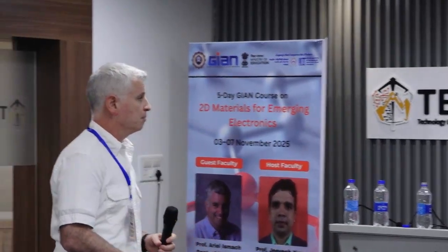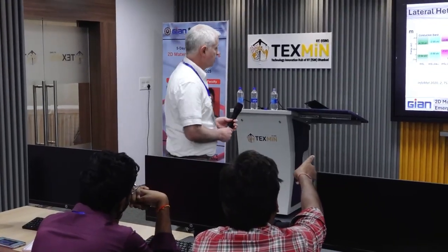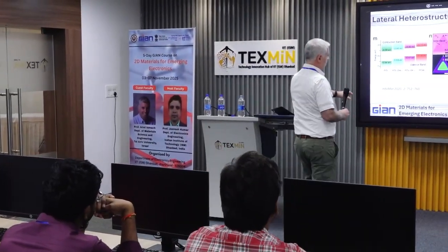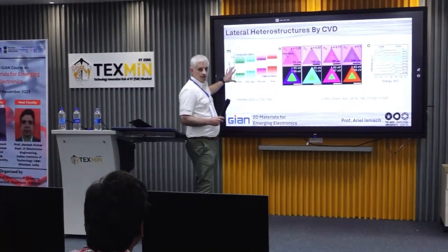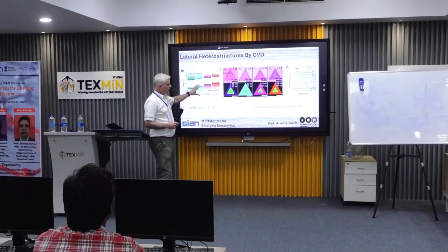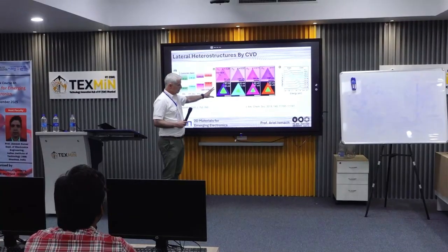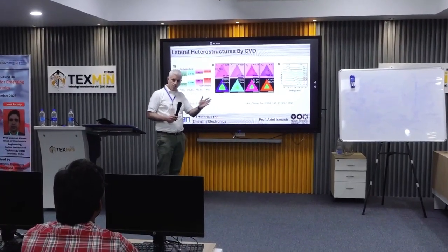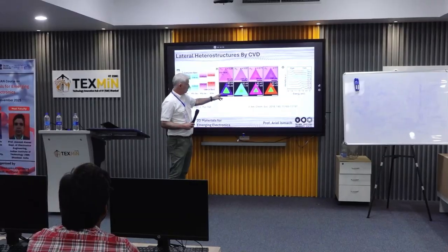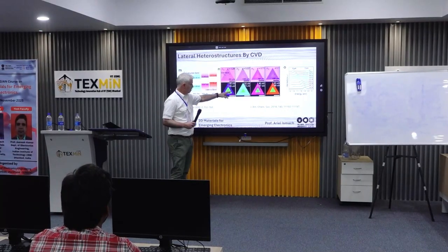So this is possible. This was done by the metal-organic type of CVD (MOCVD), not by the normal CVD. Another one: tungsten sulfur selenide has been synthesized in this state. So this is a theoretical work showing the bands, and this is an experimental work in which they switch the composition during the growth. So therefore, they were able to grow, for example, first